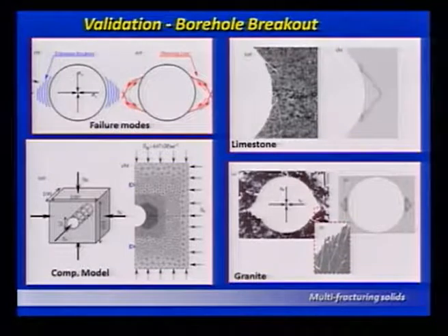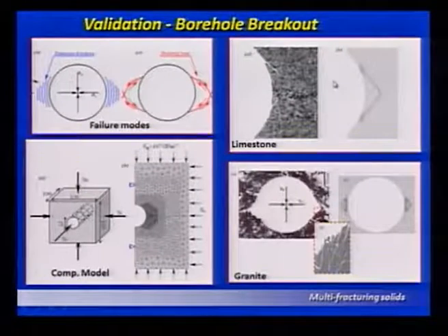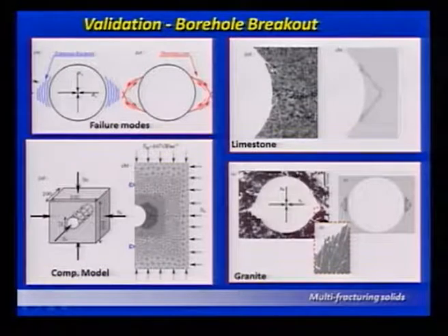On the other hand, if I just change the material properties to limestone, then the behavior is completely different. In the experiment you find that the fractures are discrete, and then in the numerical model you pick up the same kind of behavior. So you go from this kind of behavior to this kind of behavior, and the only thing I've done there is change the material properties. So this shows that the model that we're using